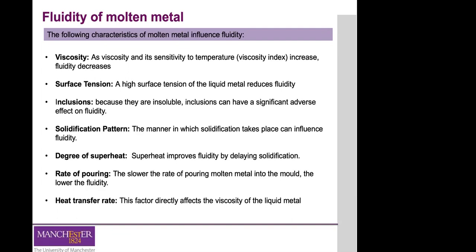Fluidity is inversely proportional to the freezing range. The shorter the freezing range, as in pure metals, the higher the fluidity. Conversely, alloys with long solidification ranges, such as solid solution alloys, have a much lower fluidity. So by increasing or decreasing the range of temperatures over which the material solidifies, we can control the fluidity and the ability of the molten metal to fill the mould cavity.